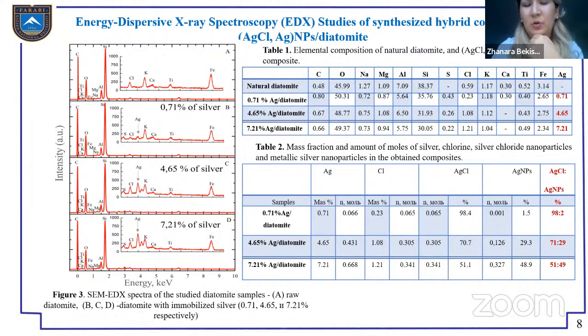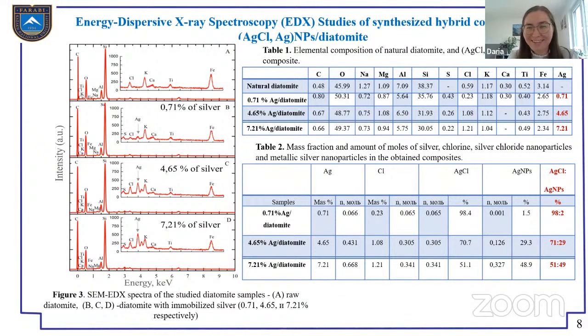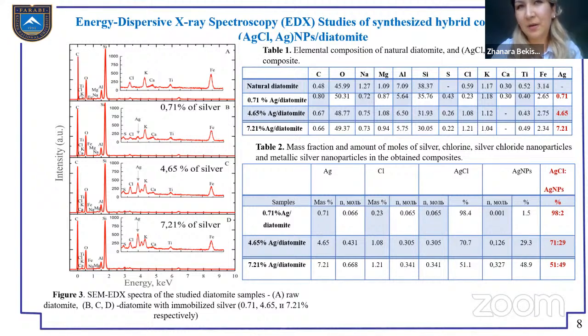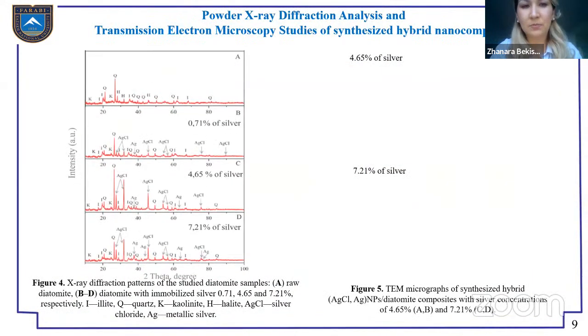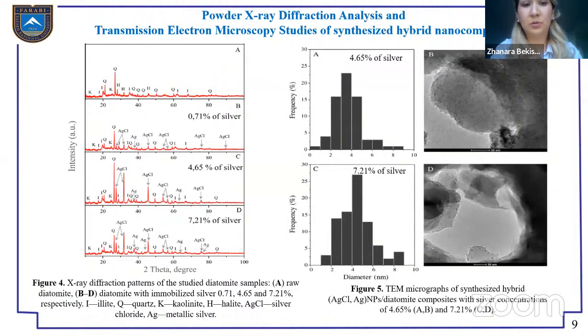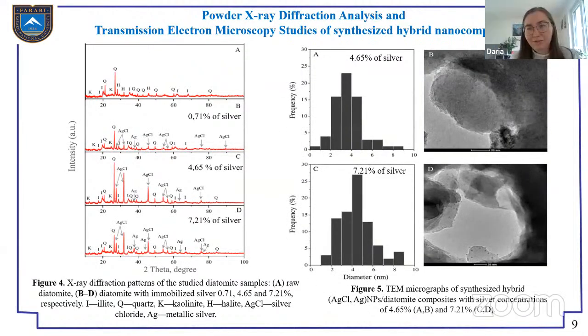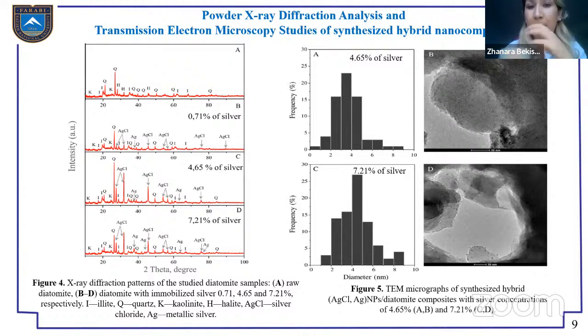Other methods to determine silver, we determined with SEM-EDX. Let's talk about silver, yes. And I know about ICP, and of course UV spectroscopy, with the peak for the nanoparticles at 480 to confirm that. And X-ray diffraction for the formation of these crystallites. That's what I know. And transmission electron microscopy for the size distribution.